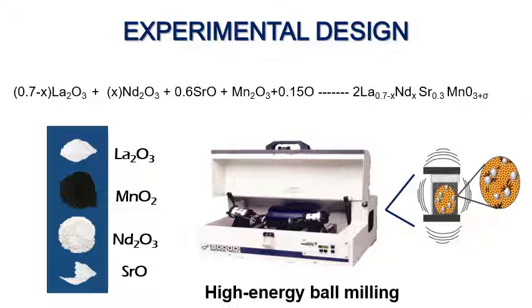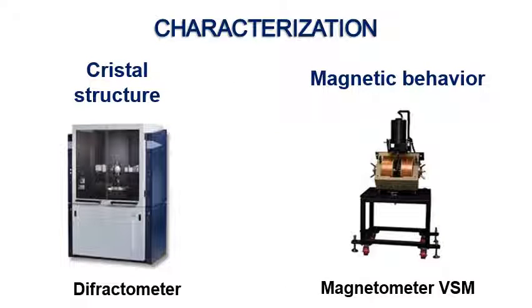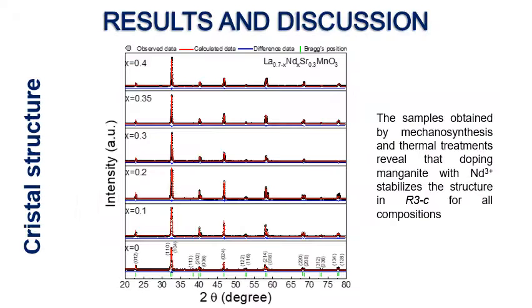This work reports the reduction of temperature on the magnetocaloric materials in manganese lanthanum strontium by doping with neodymium in a range of 0 to 0.4 mol.